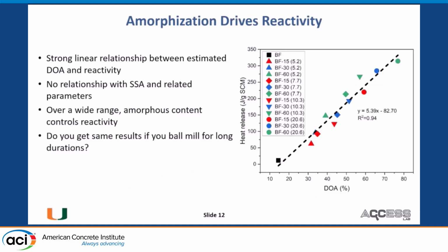So to me, this is one of the more interesting results. So I said before that the increase in specific surface area clearly results in an increase in reactivity. Actually, that's not the case. We plotted various measures of particle size and of specific surface area against the reactivity, and we did not see any correlation. Yes, we can kind of make the argument that, because of the agglomeration, etc., we probably don't have the best estimates of particle size or specific surface area, and I think that's a reasonable argument.